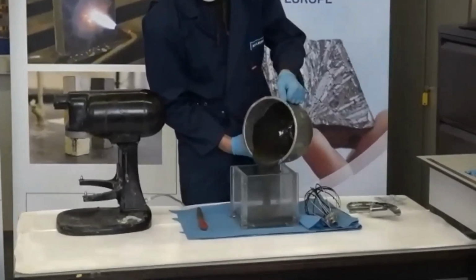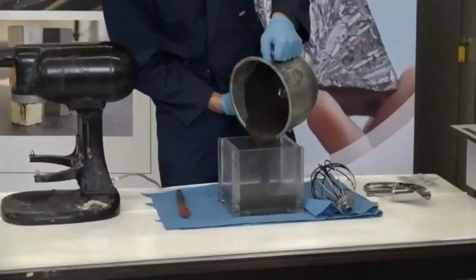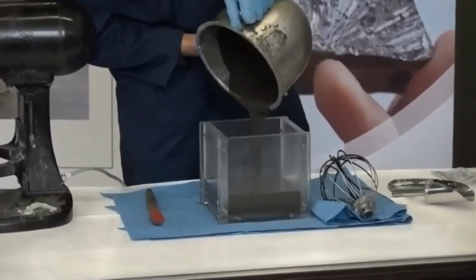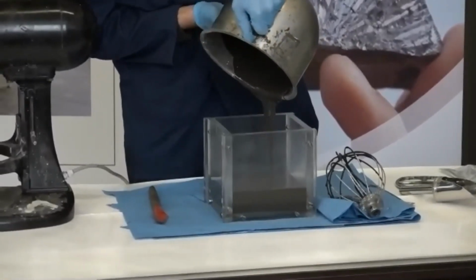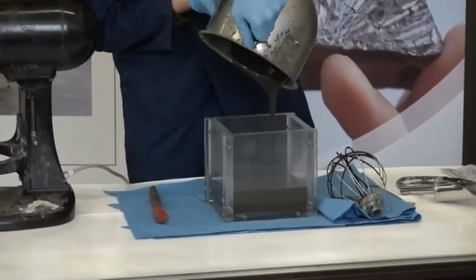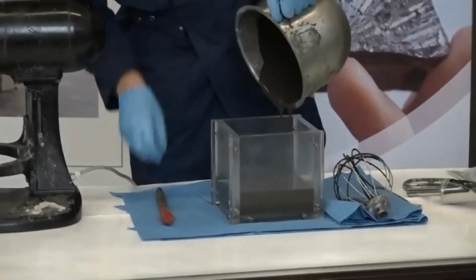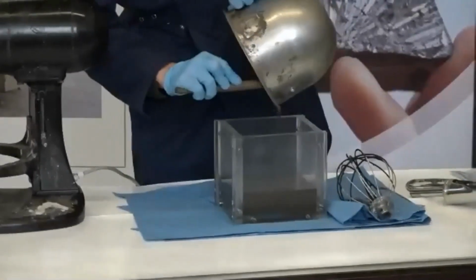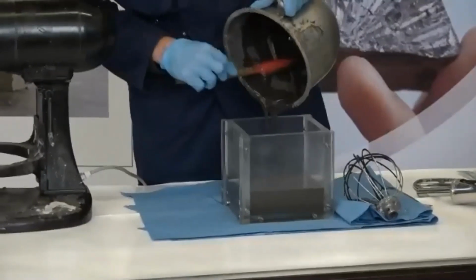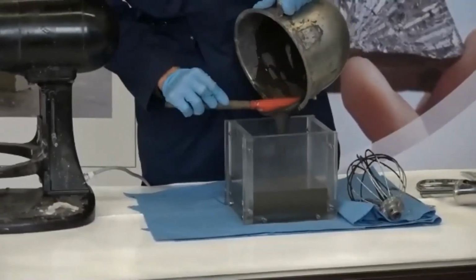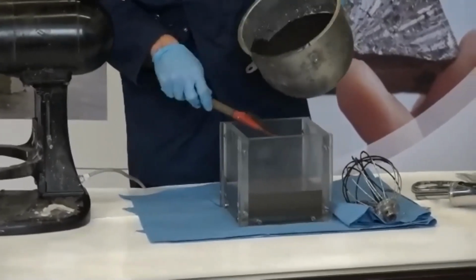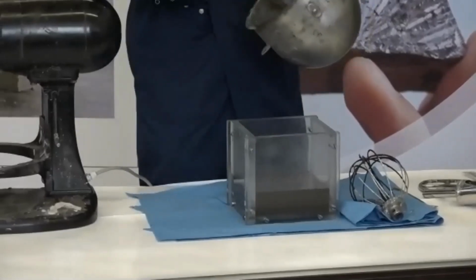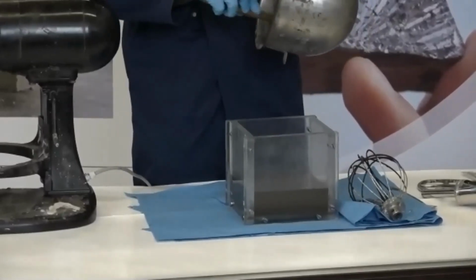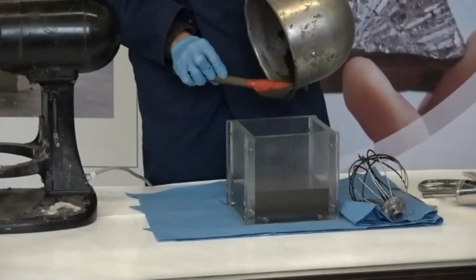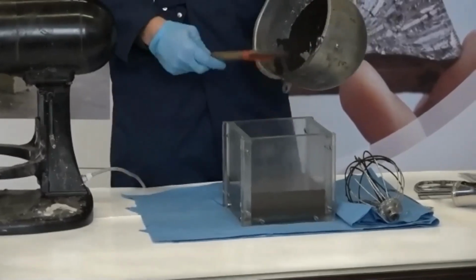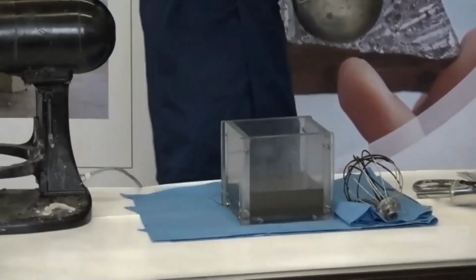Now Toby is casting this mixture in the mold that we have prepared. And as you can see, it's very flowable. So we designed it to be very flowable also for an industrial process, thinking always to upscale these samples. What you perhaps will see in some minutes or some seconds is that this mixture or this paste will start rising. And this is because we are creating these hydrogen bubbles inside of that base with the aluminum that we just add.